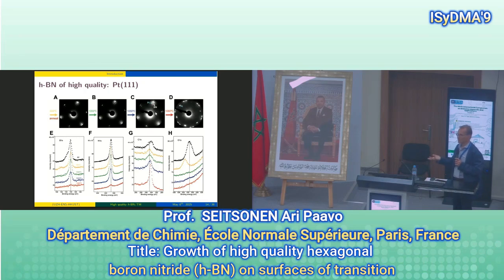So what happens is that initially you grow hBN on the substrate, but when you heat it high enough, then something happens. Probably there's some desorption, and there's the carbon which comes from the substrate. And the carbon binds stronger than the hBN. Carbon, well, it turns into graphene on the substrate. Yeah, if you didn't know, maybe some of you didn't know, this was actually probably one of the first types of graphene which was created. People just didn't know. I mean, it was much before the Scotch tape experiments. But of course they didn't know that it was a single layer graphene. But here we see that in action, so the dissolved carbon comes to the surface, and the higher the temperature, the more carbon there is, and eventually the surface is covered with graphene.